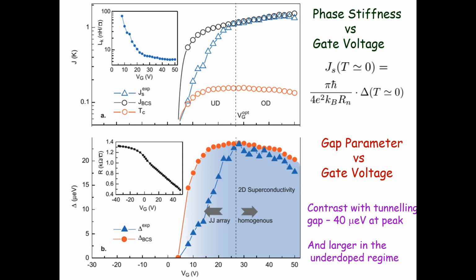And there is a very recent tunneling data on this measurement of superconducting gap. It turns out that at the optimal doping, the value is roughly about 40 microelectron volt. And this is comparable, it's slightly lower, it's about something like 22, 23 microelectron volts from our measurement. But the tunneling measurements in this regime actually show a much higher gap. And here we are measuring it much lower. Now the reason for that I think is because we are looking at the response of the condensate, looking at the phase stiffness. And if you look at the tunneling gap, it is basically coming from the single particle density of states. It does not mean that you have actually condensate there. You may have pairs, but there won't be any condensate.